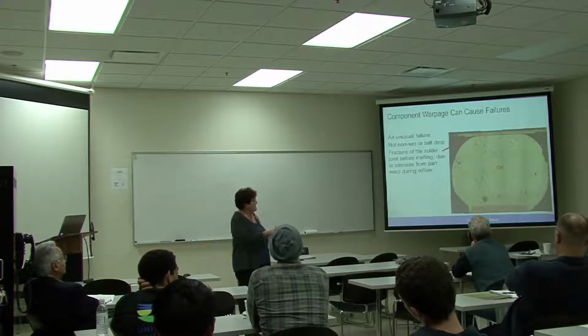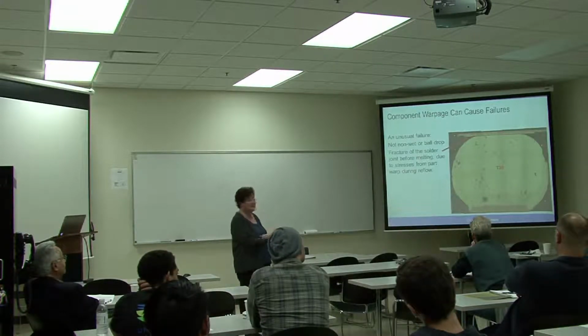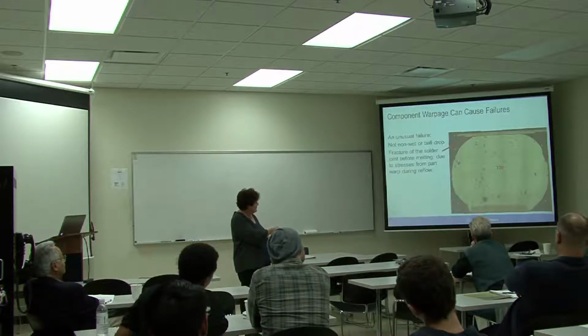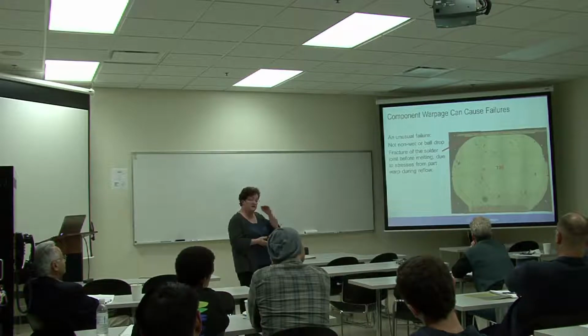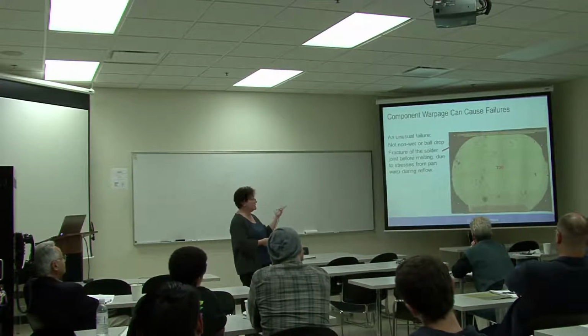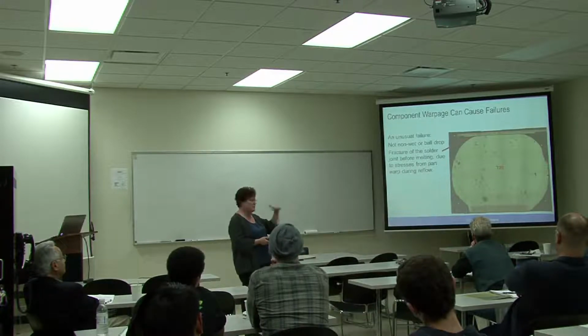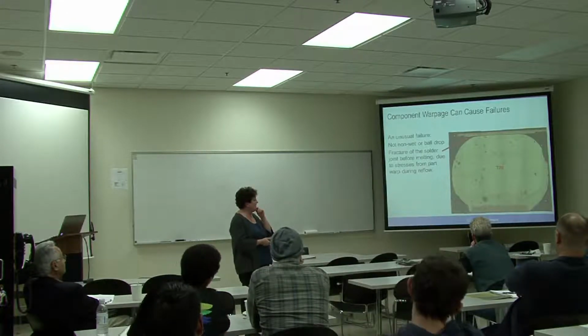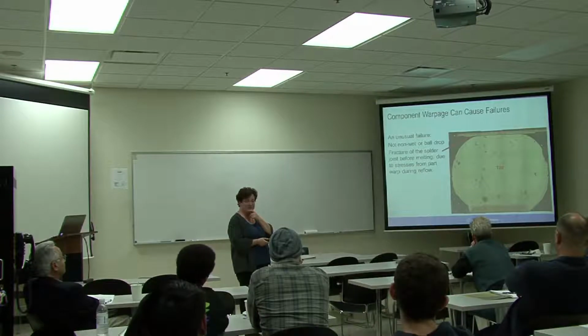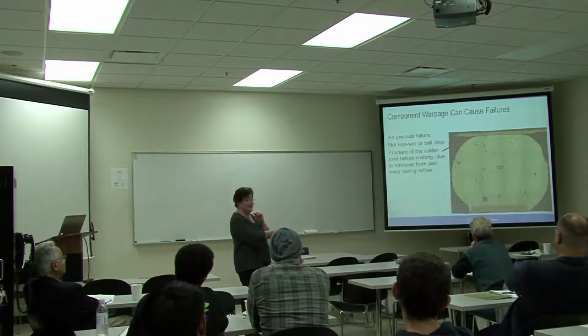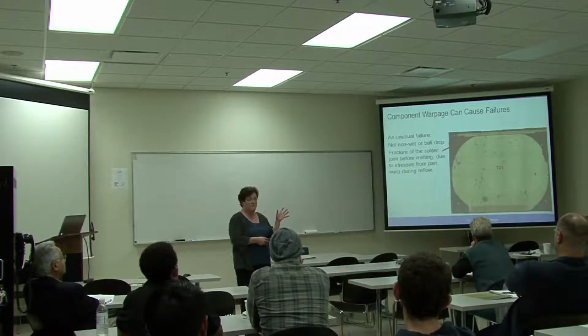But what we don't see here is a meniscus of solder right along that pad, and we don't have that either. What we can see on that side is a fracture right through the intermetallic layer. So we had a joint, we had a failure, but it's a brittle failure that snapped through that joint. So the conclusion is it did not happen when it was melted. It happened just before it melted. So this fractured, and then the ball melted, and the solution was still the same.